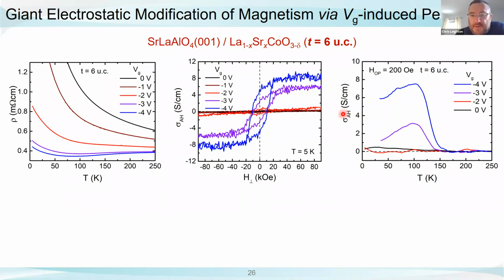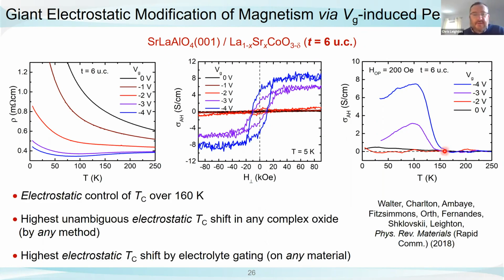We also then measured the Hall conductivity as a function of temperature. You take it from a system where there's almost none to the point where you can generate a TC, which is at least 150 Kelvin, okay? So to put that in context, for a predominantly electrostatic effect, not an electrochemical effect, that's actually the highest that I'm aware of electrostatic TC shift in any complex oxide by any method. And it's the highest electrostatic TC shift by electrolyte gating that I think has been achieved on any material. Certainly, I think it was at the time we published this in 2018.